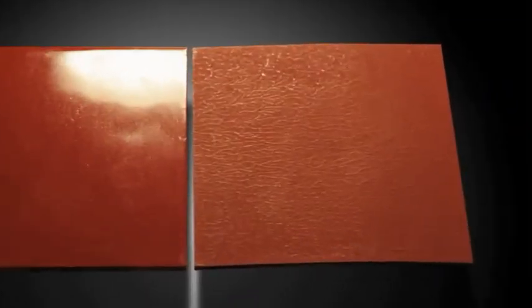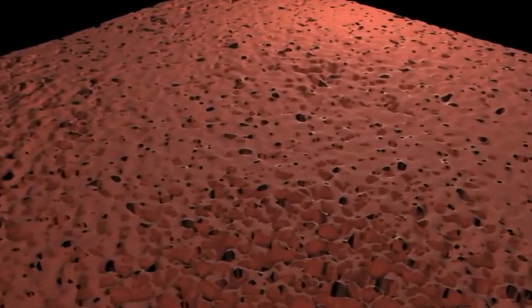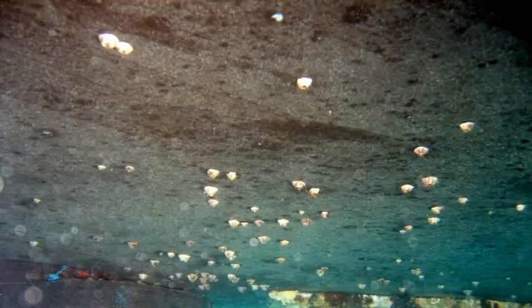On close examination of a traditional self-polishing type of anti-fouling coating, a relatively rough surface is found. The whole structure is littered with elevations, indentations and pores as a result of coarse fillers and the application process. This, in addition to cracking and loss of paint, serves as a foothold for dirt and biofouling, again increasing water friction.